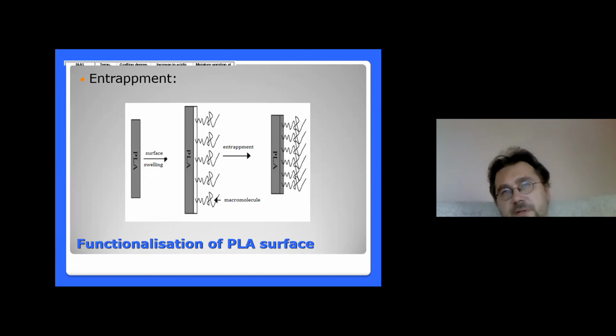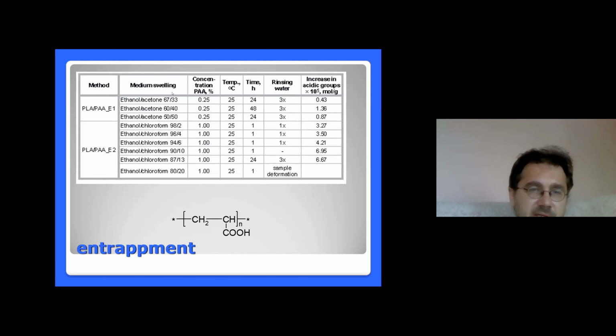Okay. The next one is entrapment, which is even easier than grafting. I'm not sure you're familiar with the entrapment idea: we take the polymer into a mixture of solvent and non-solvent. After such treatment, the external layer is more delicate, more soft. So after such swelling, we can introduce the solution of the polymer which we want to entrap inside. And after entrapment, we put the material into the non-solvent, and thanks to that, we have the modified layer. It's just a physical modification. There is no chemical connection between those materials, but it's very efficient, easy, cheap, fast, and a durable modification. It depends on the entrapment conditions, but we can change the surface.